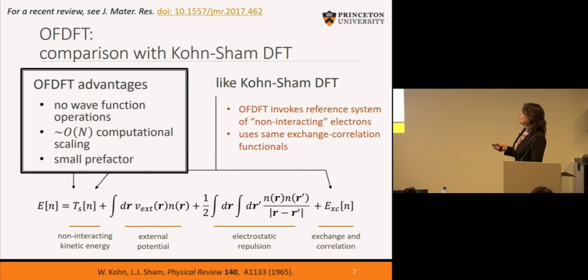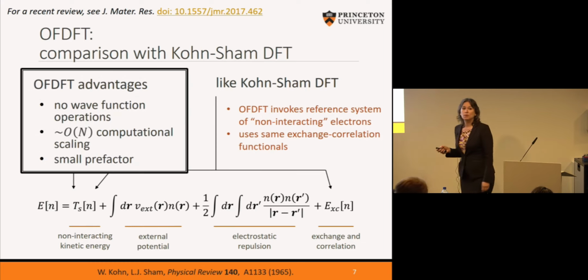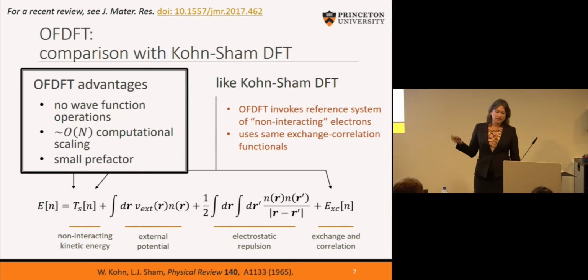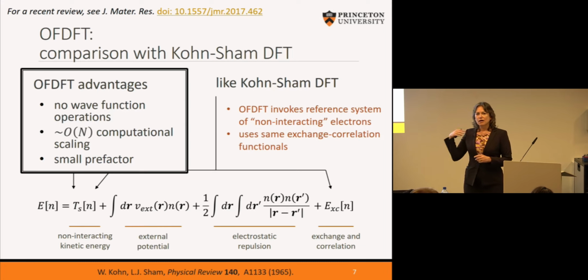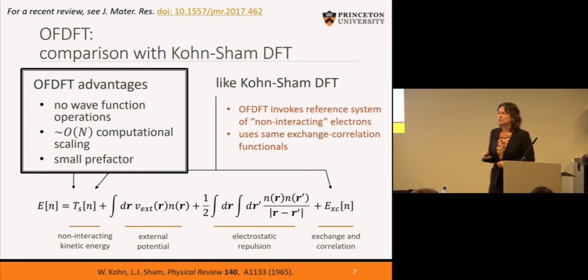The advantage of orbital-free DFT is that it's linear scaling and it has a very small prefactor. In fact, in some of the mechanical properties, for example, that we used to study in multi-scale simulations, we showed that because we don't have to do K-point sampling, et cetera, because there are no wave functions here, our calculations can be up to 5 orders of magnitude faster than Kohn-Sham theory. So that makes it so that you can do long trajectories and large sample sizes.